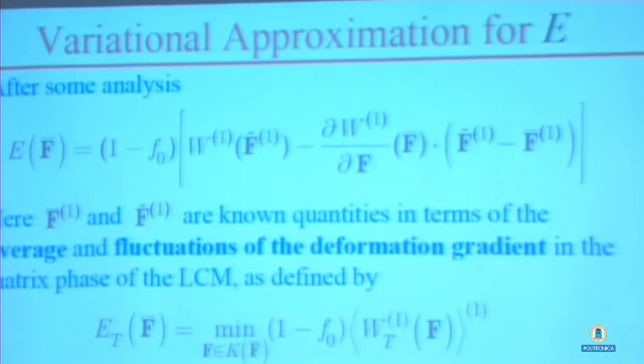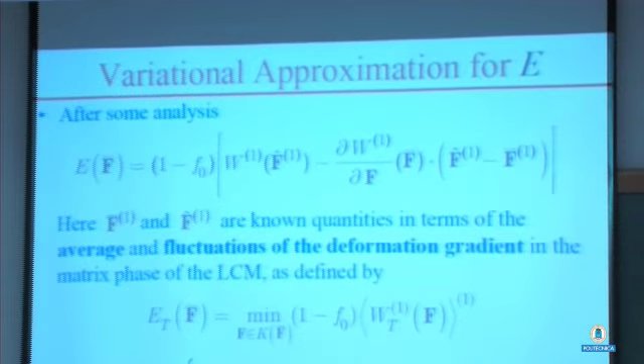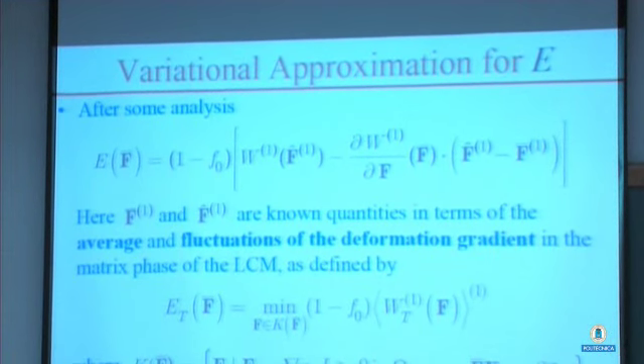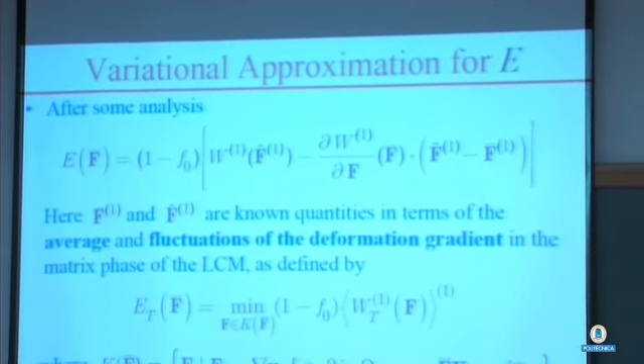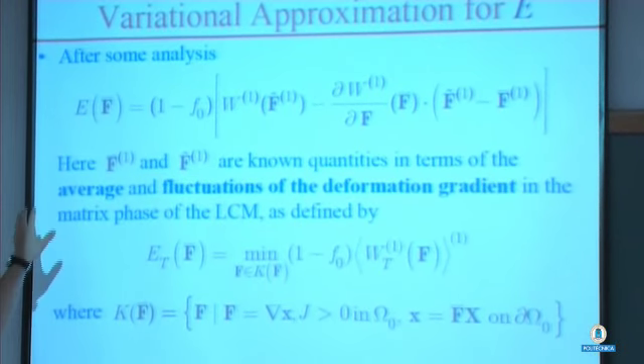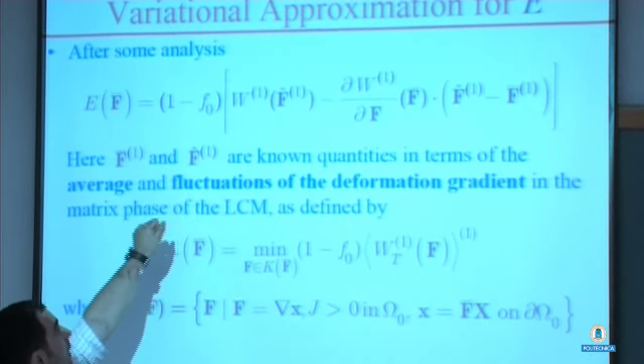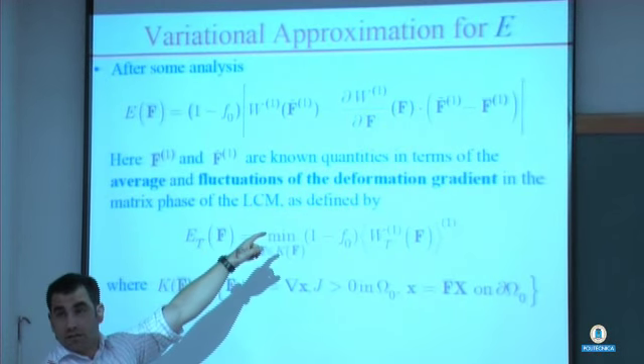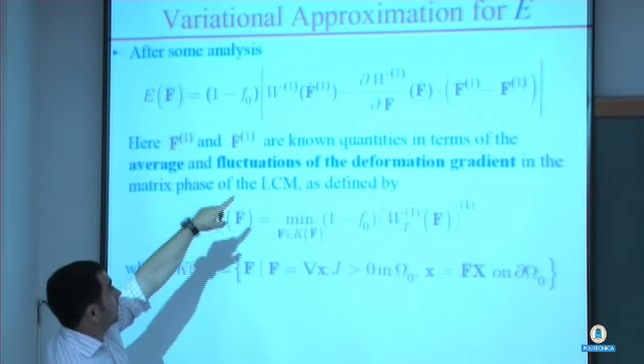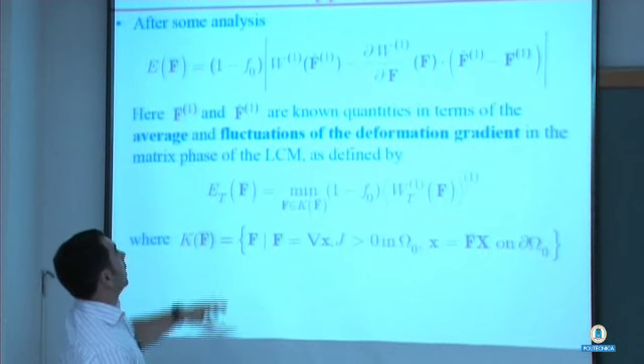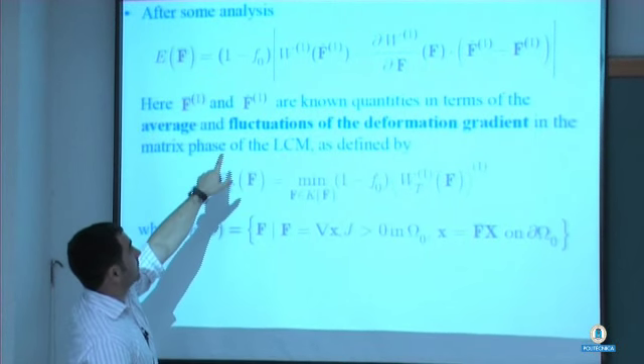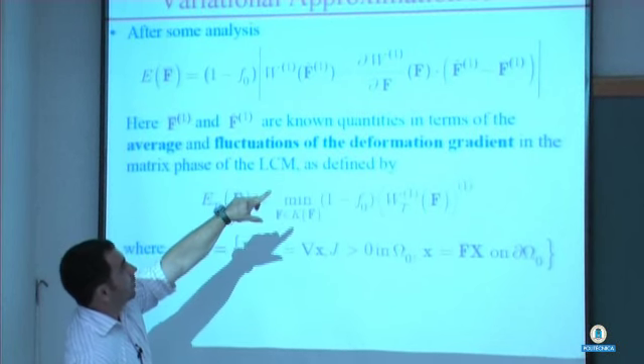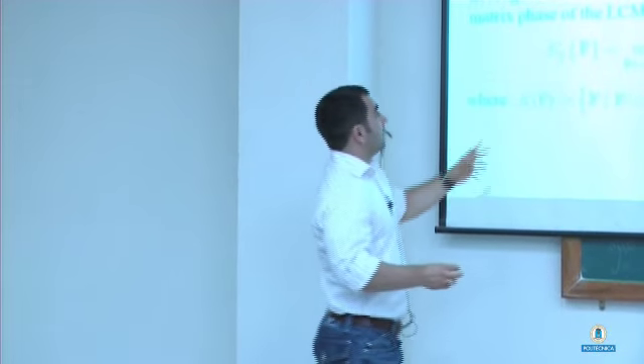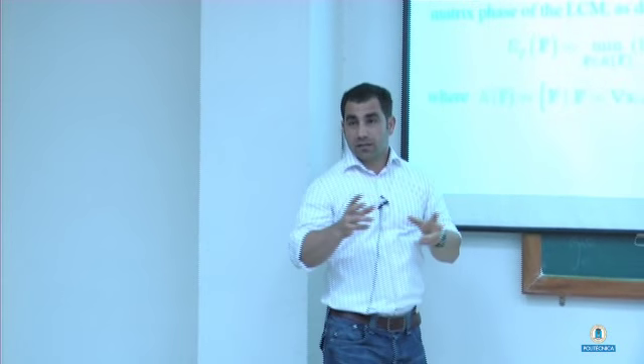Now, if we make use of this idea and do some calculations, at the end we can come up with a formula for the approximation for the total elastic energy, and it's given by that expression there. You see that it depends on W1, the stored energy function of the matrix, depends on F bar, that's the applied loading condition, depends on F naught, initial porosity, and F hat 1 and F bar 1. Now these quantities are related to the fluctuations and the average deformation gradient in this linear comparison material.